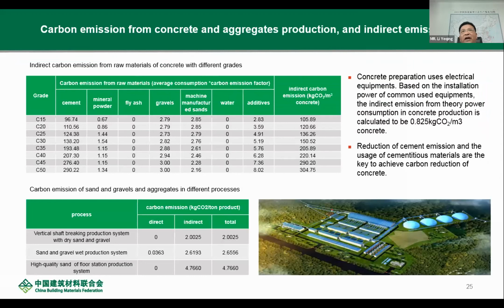There are also some emissions from the concrete and aggregates. From this table, we can see the carbon emissions from concrete with different grades from C15 to C50, including the carbon from the cementitious material, gravels and aggregates and additives. It's about 105 to 300 finally. The key to achieving carbon reduction of concrete is to reduce the cement carbon emissions and use supplementary cementitious material.